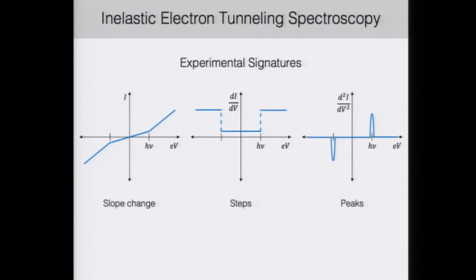And so there are several experimental signatures for inelastic tunneling spectroscopy. If you measure just the DC current as a function of bias, you'll see a slope change at this energy. If you look at the differential conductance as a function of bias, you'll see a step. And then if you take the derivative of that, you can see it even more clearly as peaks in the spectrum.